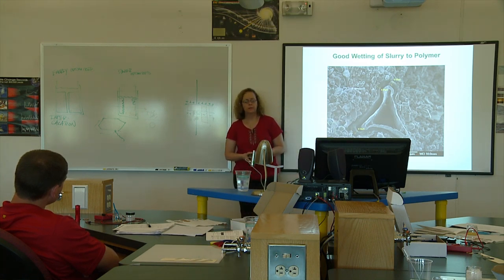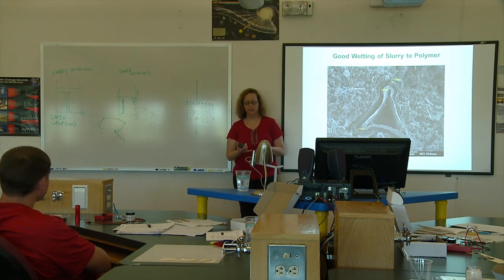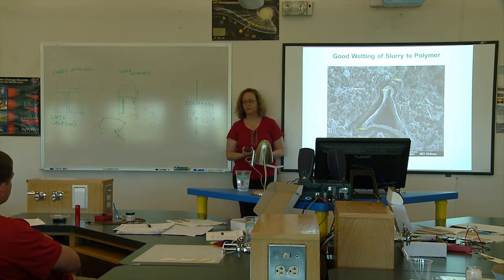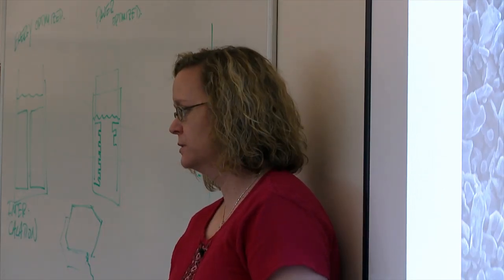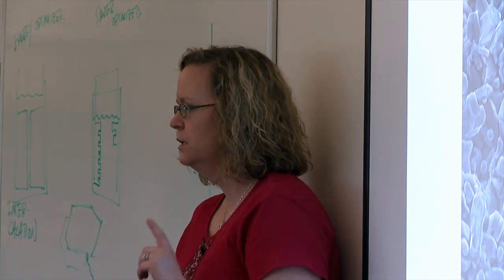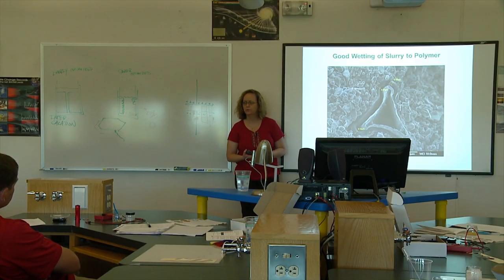So again, where we are today is the copper antimonide we know is really fast. It works, that part works really well. The slurry chemistry we've developed is also all water-based. And that's something that a lot of battery industry experts would tell you will never work, but it actually does work if you use new conductive additives. We can't use what they typically use, but we've designed some new ones that are safer and they're stable in water. But this polymer, the ionic conductivity is still too low. And by too low, I mean it's like 100 times too low.